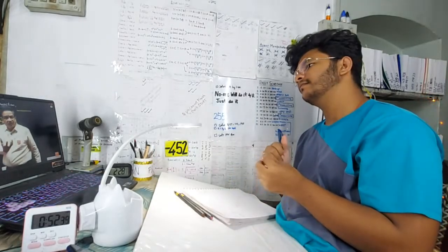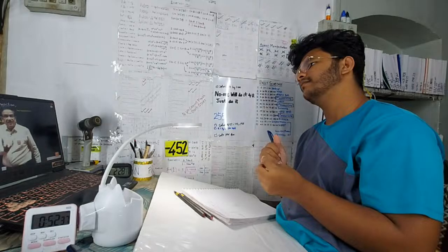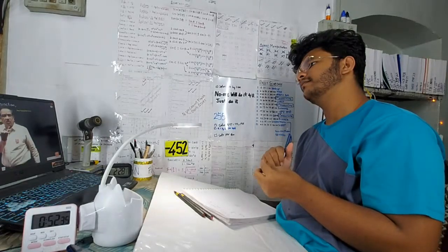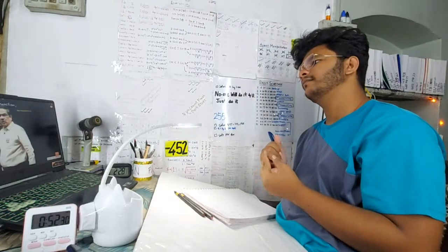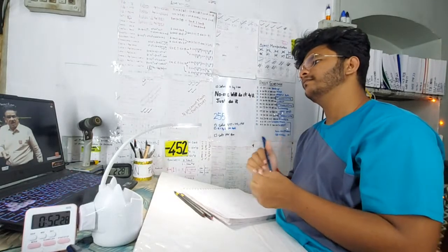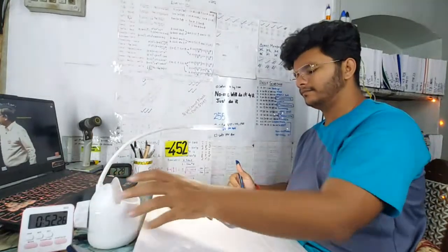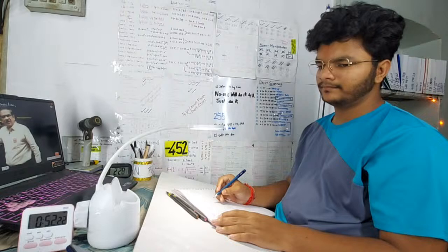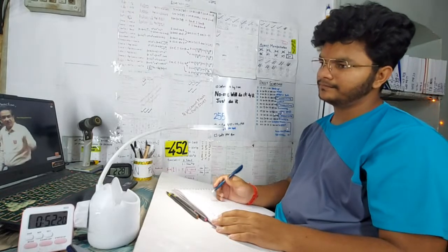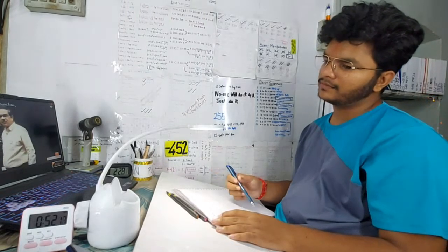So, at a few places, new phase pearlite is formed, but that new phase pearlite will have more growth rate. Therefore, we understand at high temperatures, small nucleation rate and large growth rate are associated with formation of coarse pearlite. So, at high temperatures, coarse pearlitic structures will be formed. At very small temperatures, fine-grained structures are going to be formed. This is the conclusion that we can make from here.